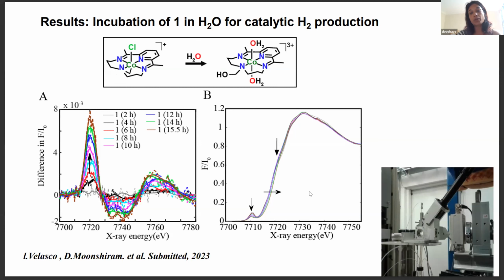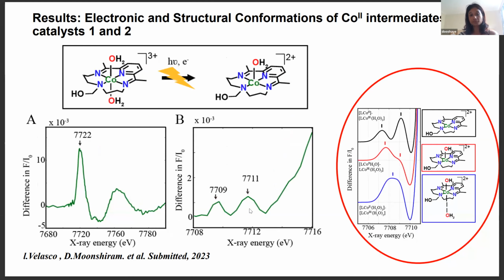As well, here we have the laser-off spectra. So just looking at the ground state, we see gradual isosbestic points and change from catalyst 1 to catalyst 2. So a decrease in the 1s→4p shakedown transition, a shift of the rising edge due to loss of the chloride ligand, and a decrease in the pre-edge feature as it becomes more centrosymmetric.